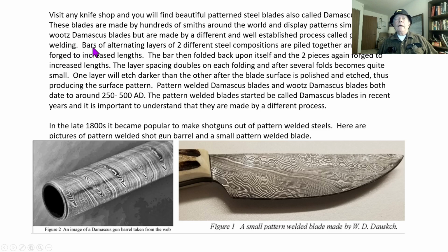Now, the way they make them is they take bars of alternating layers of 2 different steels, so they have different compositions. That's important. They pile them together, and they hot forge them together. That welds the alternating pieces together, increases the length. After the length gets long, they fold the bar back on itself, and then reforge it again, repeating the process. So the layer spacing doubles on each folding.